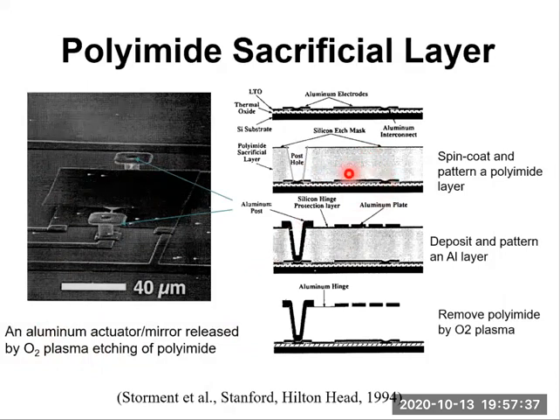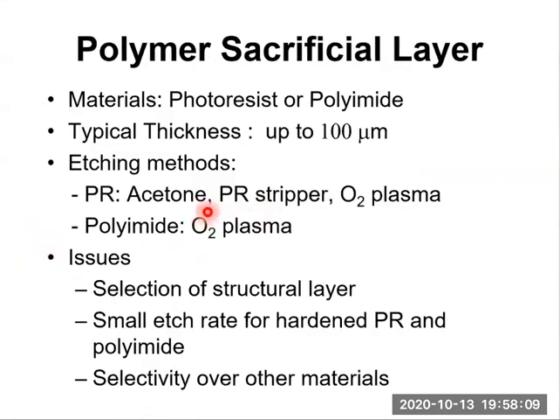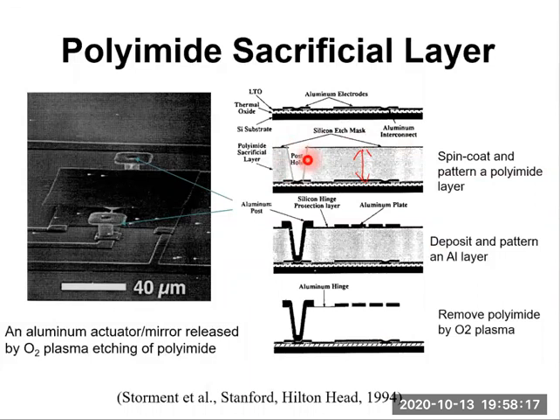Let's take a look at the specific fabrication process. After fabricating aluminum electrode and other structures on the substrate, a polyimide layer, note that this thick layer stands for the polyimide layer, is spin coated and patterned. Note that in this step, this post hole is patterned in the polyimide layer.